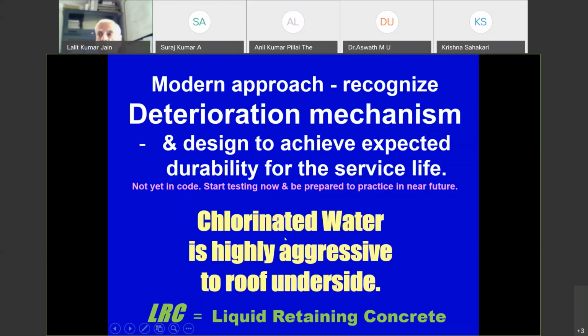Most of the time we are using chlorinated water, and the chlorides are available throughout the life of this structure, and these chlorides penetrate in. So what is the rate at which they can penetrate, and when do these chlorides reach the reinforcement surface? When the concentration of ion at the reinforcement reaches a particular level, the resistance of the concrete to corrosion of the steel is broken down or reduced, and corrosion can start.